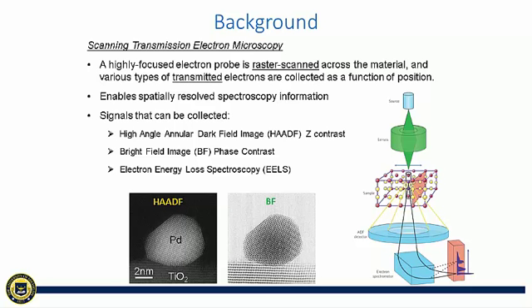For example, when the probe is raster scanned across the sample point by point, then we can know the chemical information point by point. By installing different detectors, different signals can be collected simultaneously. For example, if we collect electrons that are scattered at high angle with respect to the optical axis, then we'll form a high-angle annular dark-field image. It's similar to Rutherford scattering, so it is a Z-contrast image. The higher the atomic number, the brighter it will appear in the image.